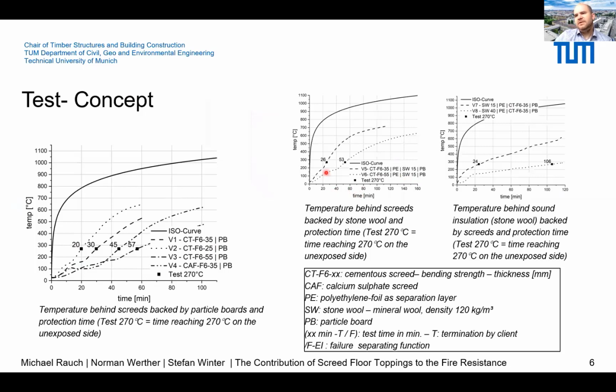This shows the influence of the backing material. For example, for the screed with a thickness of 35 millimeters, the temperature of 270 degrees was reached 4 minutes earlier compared to a backing material of a particle board. And in the next diagram, you can see test number 7 and 8. There, the stone wool was directly exposed to the fire and the screed was used as backing material. This shows a positive effect of the screed as a backing material compared to the particle board as a backing material.